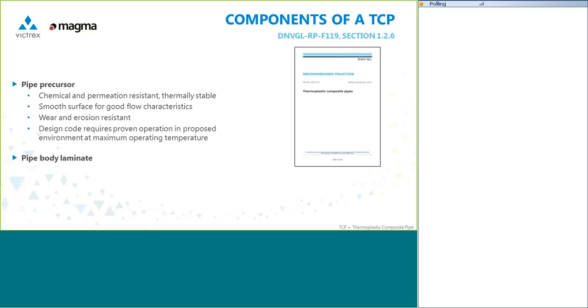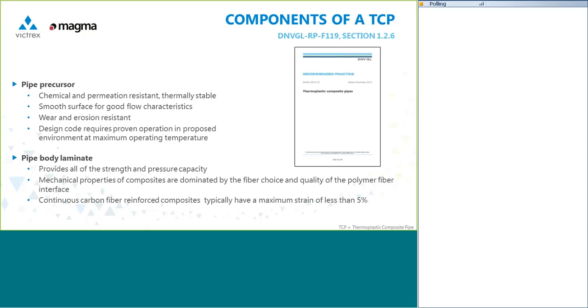Then there is the pipe body laminate. That is the kind of the guts of the construction. The pipe body laminate provides all of the strength and pressure capacity of the thermoplastic composite pipe. Obviously, the mechanical properties of composites are dominated by your fiber choice. First and foremost, if you have a carbon fiber composite, that is going to dominate the properties. But also the quality of the polymer fiber interface. That fiber matrix interface is extremely important, and we'll say a little bit more about that in a few minutes' time.